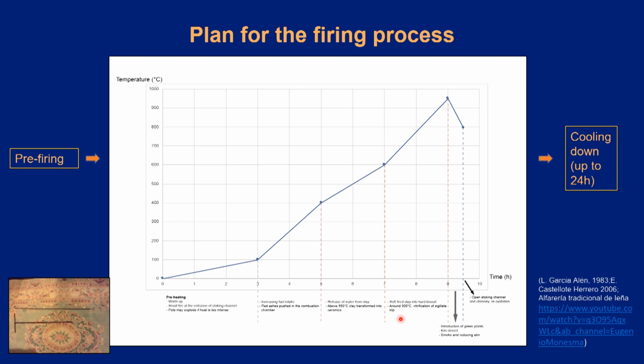When thermocouples indicate temperature above 850 centigrades, we will start taking painted samples to check slip sintering and vitrification. From gas test firing, we expect that our sigillata slip will vitrify at temperatures around 900 centigrades. When slip is vitrified, we will introduce green plants and close the stoking channel and chimney to produce smoke and reducing atmosphere. The pots will turn into a grey or black color.